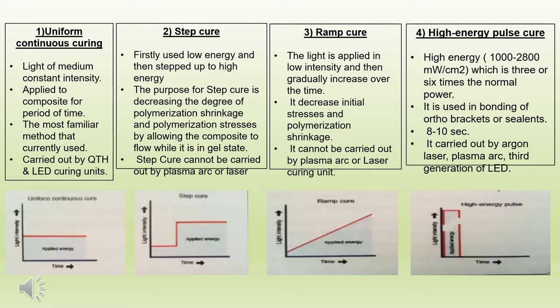In uniform continuous curing, light of medium constant intensity is applied to the composite for a specific period of time. In step cure, firstly we use low energy and then it is stepped up to high energy. The purpose for step cure is decreasing the degree of polymerization shrinkage and polymerization stresses by allowing the composite to flow while it is in gel state. In ramp cure, the light is applied in low intensity and then gradually increased over the time. It decreases initial stresses and polymerization shrinkage.